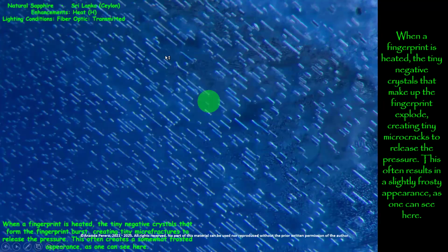What is it here? The lighting condition here is fiber optic transmitted. It is also a heated sapphire from Sri Lanka. Look at the negative crystals here. Inside the fingerprint, these are the negative crystals. When the fingerprint is heated, the tiny negative crystals that make up the fingerprint explode, creating tiny microcracks to release the pressure.